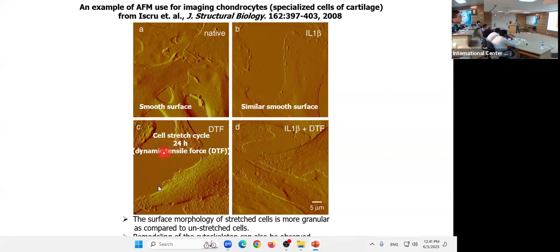And then after 24 hours, they saw a significant reorganization of the actin cytoskeleton. The surface was more granular compared to the control cells, and the shape of the cell changed. You can see very closely also that there are vesicles translocating to the cell surface. There are filaments present inside the cell that could very nicely be detected using the atomic force microscope. When they combined this with IL-1 beta, they saw a different profile.